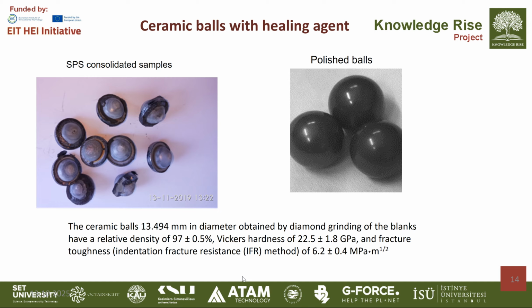Here you can see the SPS consolidated samples in a near ball shape, and these SPS consolidated samples could be polished precisely into ceramic balls with a specific diameter of around 13 millimeters. These balls have a high relative density, around 97% of theoretical, high Vickers hardness and fracture toughness.